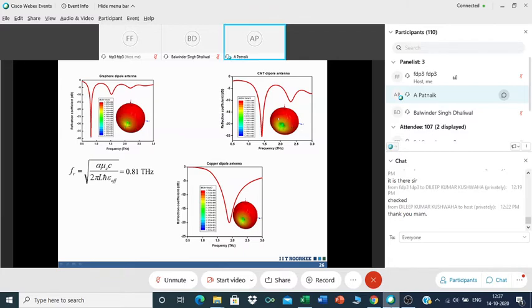Second one, carbon nanotube, is resonating at roughly around 1.4 terahertz frequency, whereas the copper one is working at nearly 1.8 terahertz frequency. Although all are giving the same type of radiation pattern, we found that graphene is able to resonate at a very low resonant frequency.